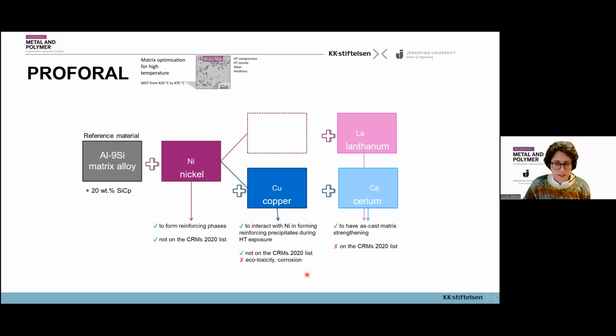Copper is also not on the critical raw material list, but it is a little bit more problematic in terms of environmental pollution because of its toxicity and also susceptibility to corrosion. We also looked into the possibility of adding lanthanum and cerium, so two rare earths, since they have been shown to have as-cast matrix strengthening in aluminum silicon alloys, but those are elements on the critical raw material list. So we explored that possibility to see if it was worth taking in critical raw materials, but having a very clear advantage in terms of mechanical performance.